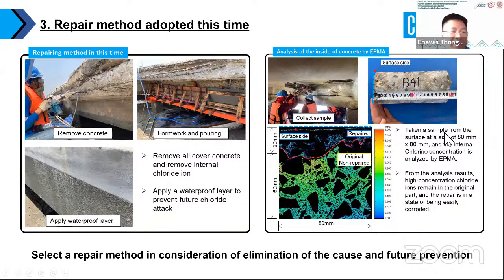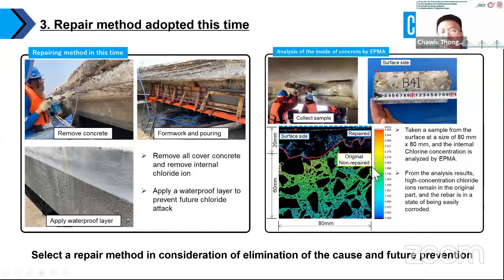On the other hand, this is a core sample of the existing structure. The internal chloride concentration inside this sample was investigated by an electron probe microanalyzer, which we call EPMA. Then we see the chloride distribution here, in combination with an electron microscope and wavelength techniques. The result is shown as a contour diagram like this. The blue part indicates low chloride density, while the yellow and green parts indicate high chloride density.